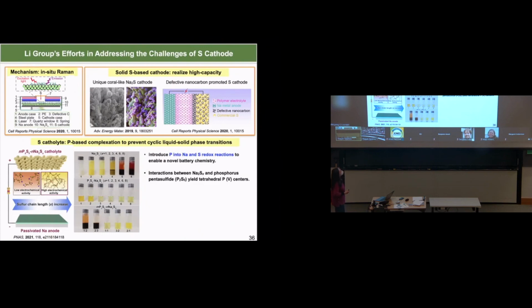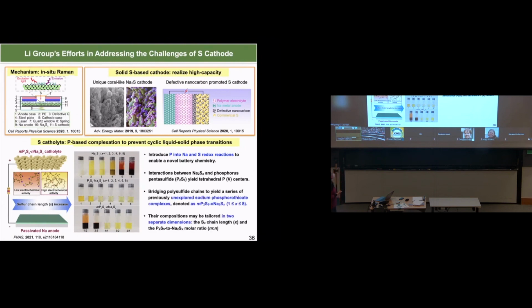Okay, so we introduce phosphorus into the sodium sulfur redox reaction, and we actually achieve a series of what we call a catholyte, a liquid complex material that can be dissolved into a different solvent system. For this material, it has a very long name: the sodium phosphorothioate complexes. We use P2S5 and Na2S. So we use this formula to indicate this series of new complex materials we have synthesized.